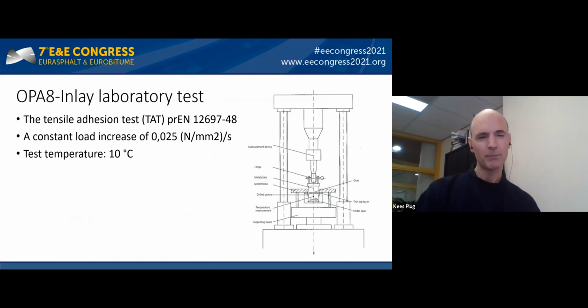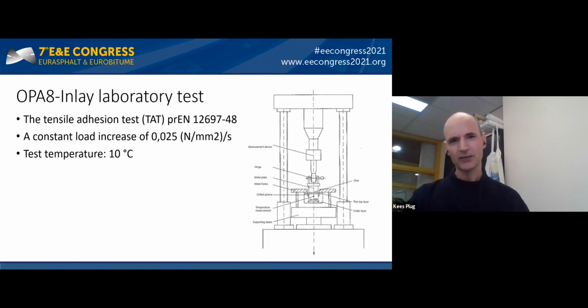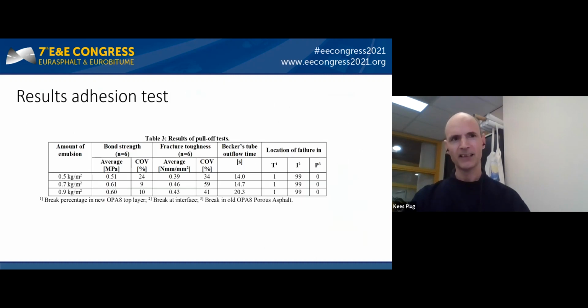Cores were drilled from the plates and tested according to the tensile adhesion test at 10 degrees Celsius. This picture shows the test setup. The results of the adhesion test show that the failure occurs at the interface between the new and the old OPA 8. The best results were obtained with the 0.7 kilo square meter amount. It was decided to use this amount as medium amount for the bond coat in the trial section.